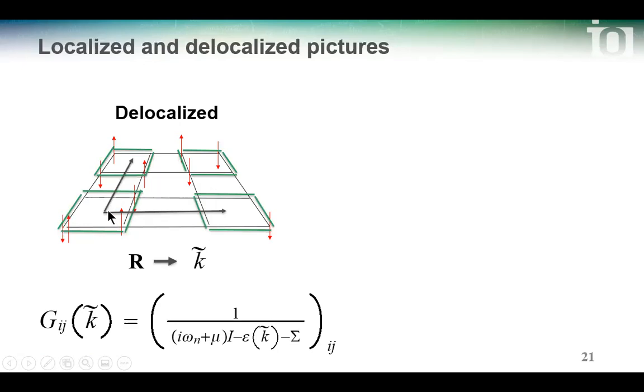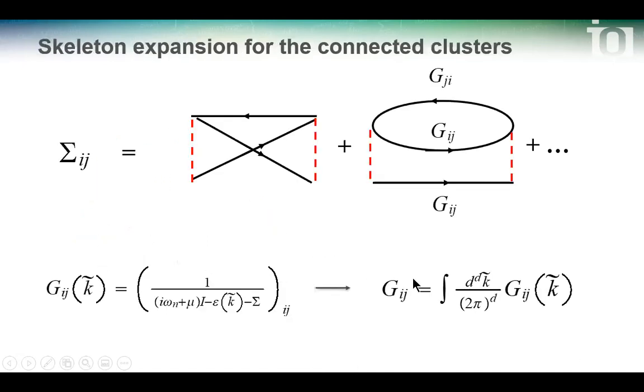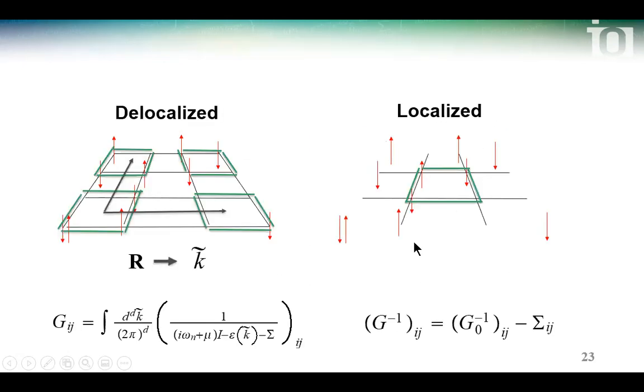Now look at the delocalized picture. Assume that you tile the infinite lattice with these squares. So if you tile the infinite lattice with these squares, you can still hop from one square to the other. So there's some energy k tilde. The Brillouin zone is now smaller because you have a bigger unit cell. And so the energy here will depend on this wave vector, but the self-energy here depends only on ij on every site. So the way to solve this problem is to solve the same skeleton expansion with the Green's function ij that is just projected back to the cluster. So the power of this is that there's a self-consistency relation now between the lattice and the solution to the localized problem. The self-energy is the same in both cases.